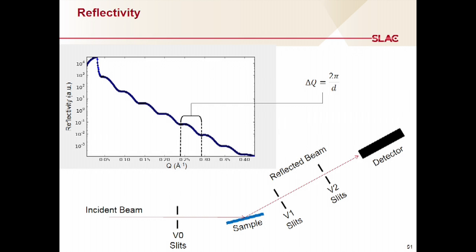This is what data would actually look like. Below the critical angle, sometimes things are a little bit funny because your sample is not always as long as the footprint of the beam is. And so if the footprint of the beam would be bigger than your sample, you only reflect from the fraction of it that's actually on the sample. And so you can get this strange shape that moves up as you change the angle.